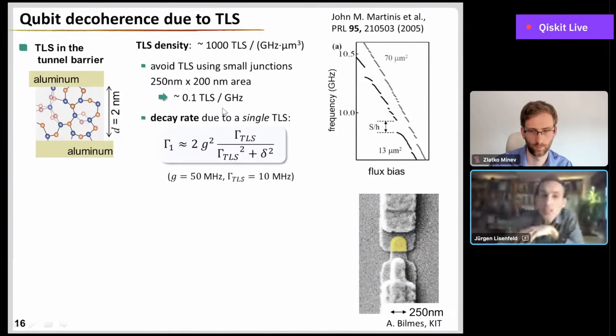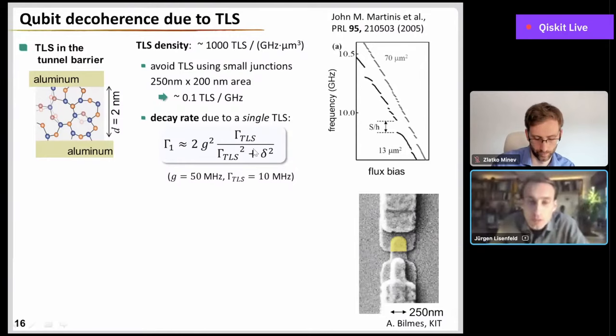But you can just estimate the decay rate, which is only due to a single defect, that the qubit, which itself would have an infinitely long T1 time, would experience. And this decay rate is just given by the product of the square of the coupling strength here between qubit and defect, which can be up to 50 megahertz, as I told you, and this is a Lorentzian resonance function, which has here the resonance of the defect, where this decay rate of the defect is this 1/100 nanoseconds that I've shown you before. And that is the detuning between the defect and the qubit.